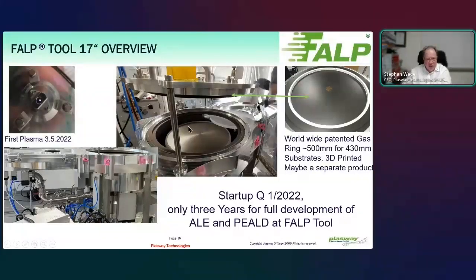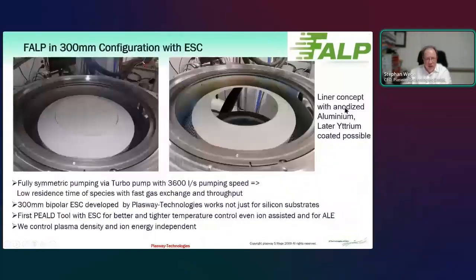Here's a first picture of our system in May 2022. So this is a 17-inch system, and at that time we really worked with a big 17-inch quartz substrate where our customer would like to have an ALD deposition. In fact, this was the first time that we saw light. This is first plasma in May 22. From that on, we developed our processes with this 500mm ring.